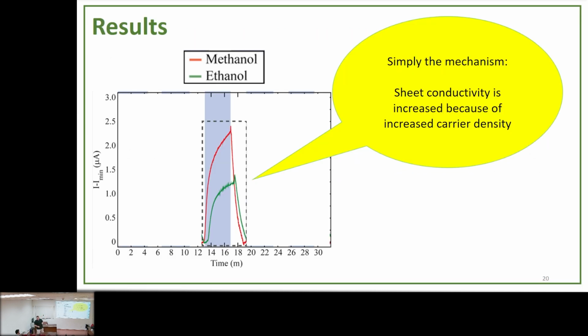What about the results? So the first result, mainly what's the mechanism? We have a base current. I set it to 0. Then there's an increase because of incoming methanol and ethanol molecules approaching the surface. The sheet conductivity of graphene, molybdenum disulfide, whatever it is, increased because of increased charge density. Because of electrostatic interaction with the surface and charge transfer between surface and molecule, you see an increase in the base current. It's simply like this.